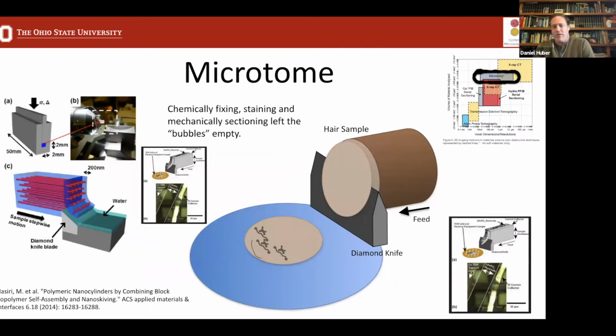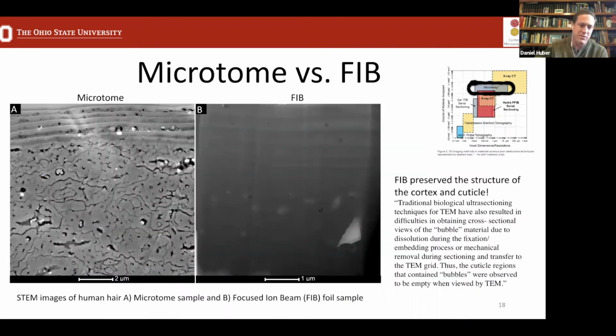The other attempt they used was microtome, using a very sharp diamond knife, taking serial slices from the hair to look at the internal structure. What they found was that with the microtome, with resin embedding and lifting out of the thin section through water, there was some degradation in the cortex material. There were possibly also some little defects showing up inside the cuticle layers, and they weren't maintaining the highest fidelity in those layers. So we were able to take the DualBeam FIB, section into the outside of the hair, look at the inside, and see that we're able to preserve the cortex and the cuticle material, and that we might be able to do TEM and other analysis using the FIB.